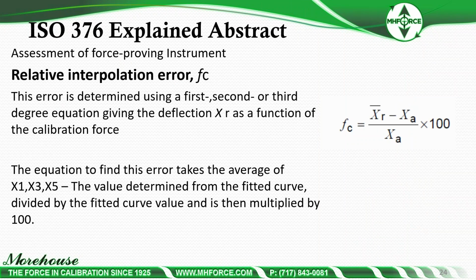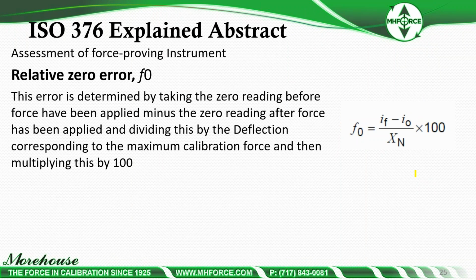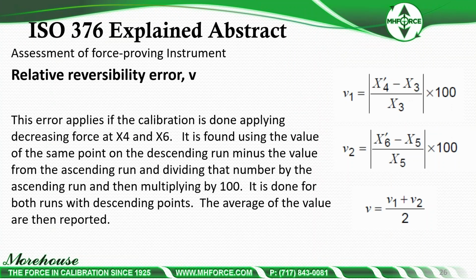Then we have interpolation error. This error is determined using first, second, or third degree equation, given the deflection XR as a function of the calibration force. That's how you calculate that. Relative zero error. The error is determined by taking the zero reading before forces have been applied minus the zero reading after force has been applied, and dividing by the deflection corresponding to the maximum calibration force, and then multiplying this by 100. Then you have reversibility error.